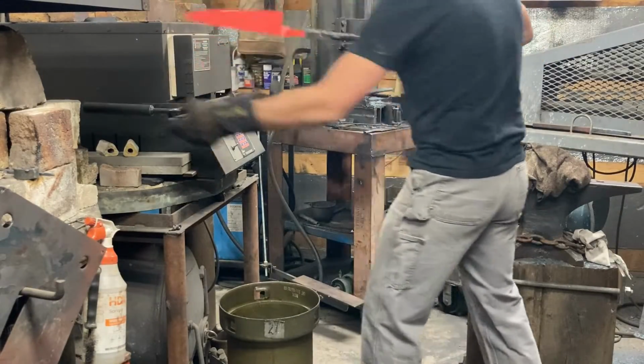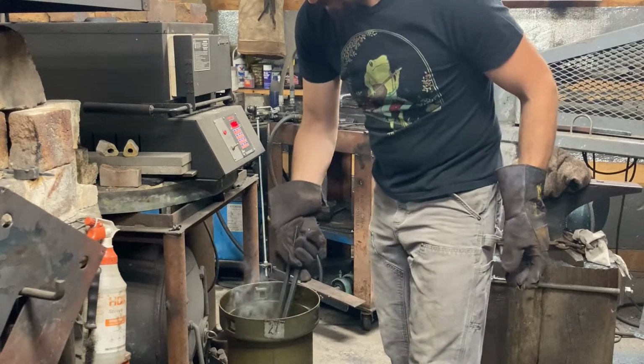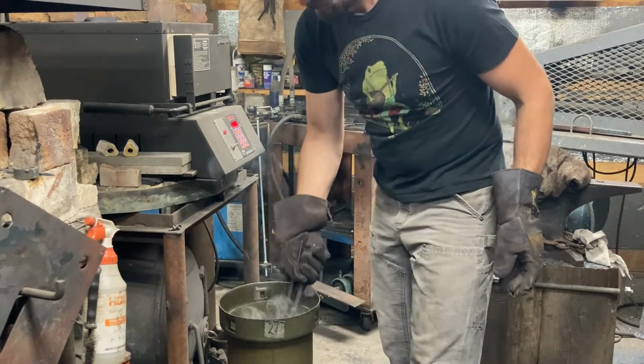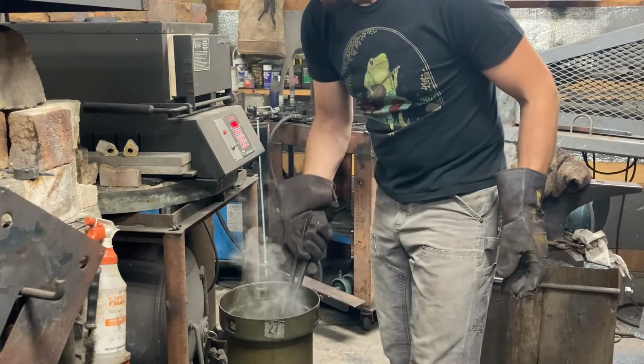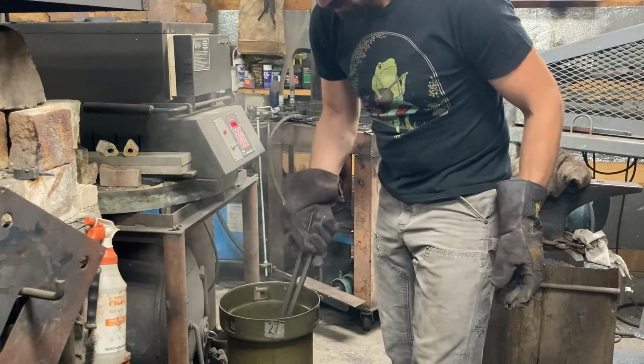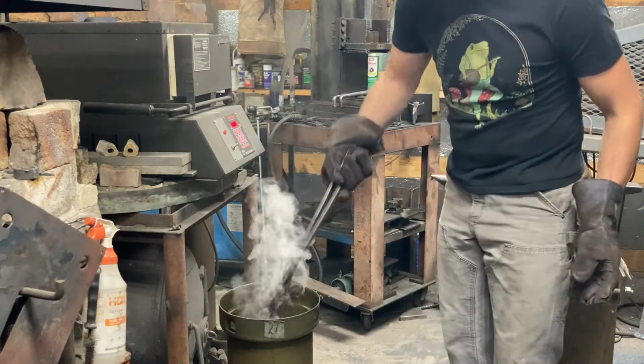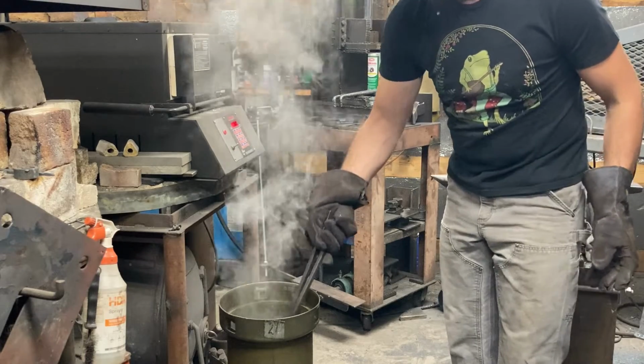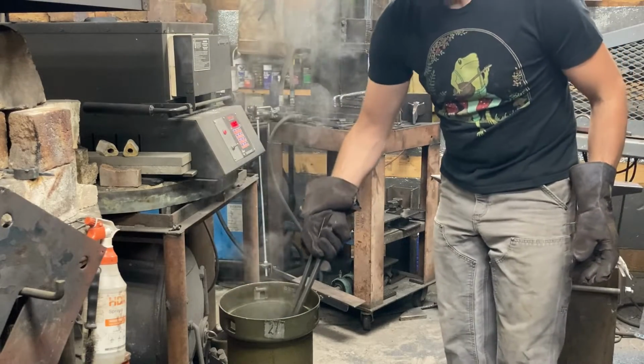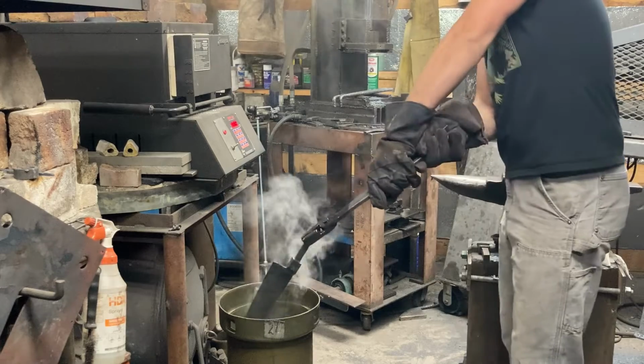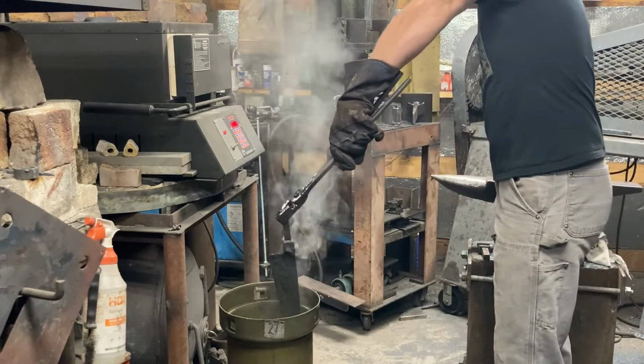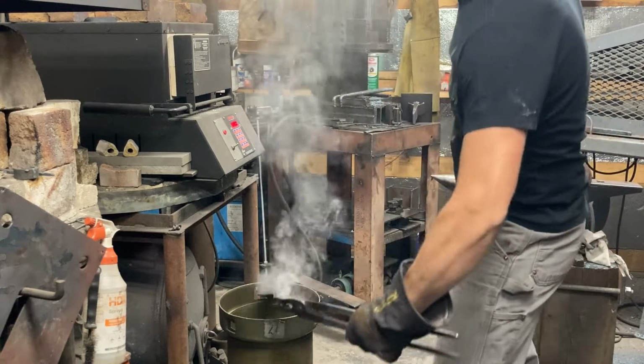I'll walk you through the quench here a little bit. So duck them right in the oil out of the oven. I do keep the door closed. I'm going to interrupt this quench after about 10 seconds. Pull it out. Still a little too smoky. Put it back in for a couple seconds. We'll pull it out again when it's slightly less smoky. I know I got a good quench on the blade.